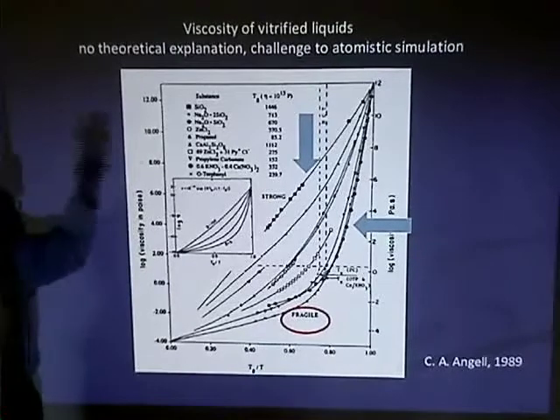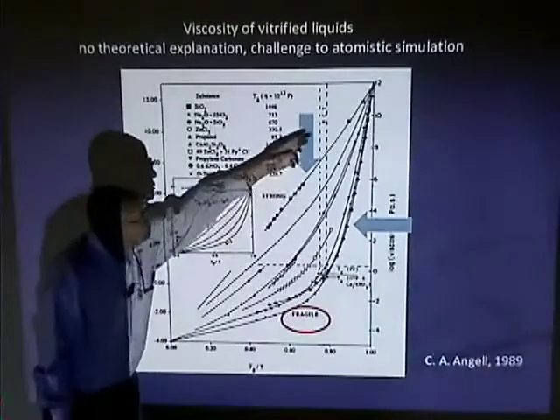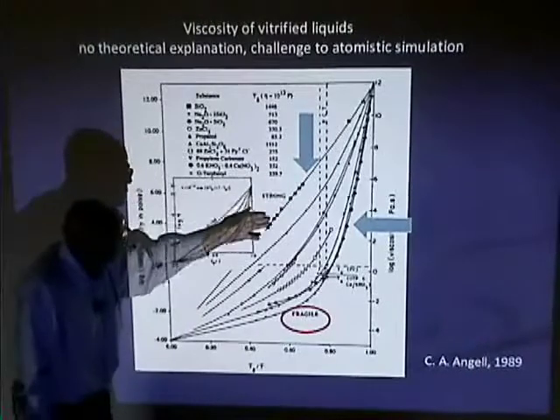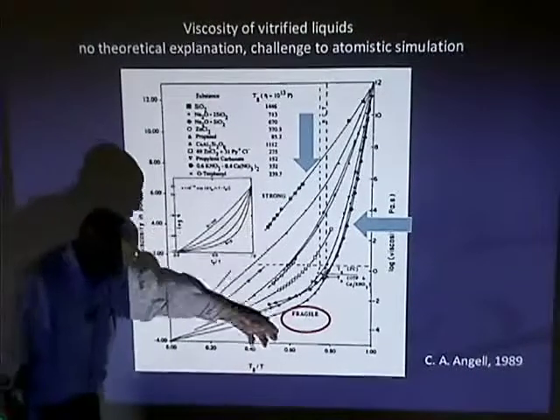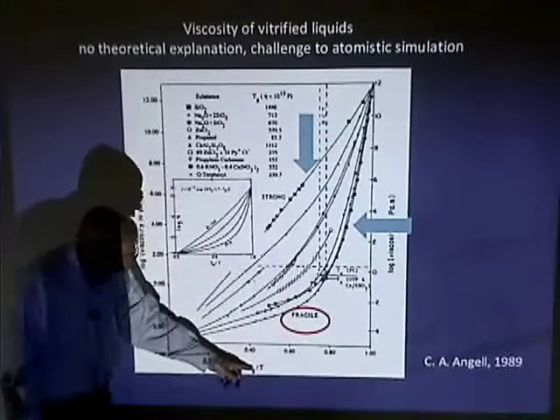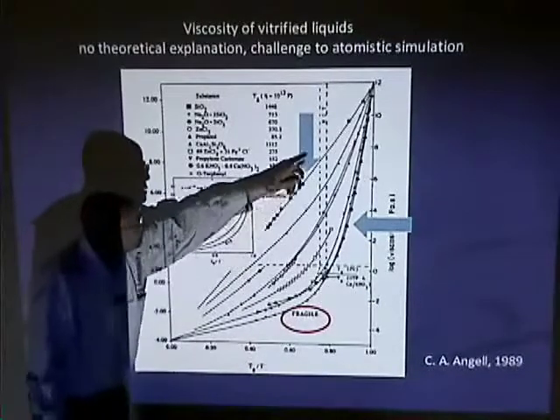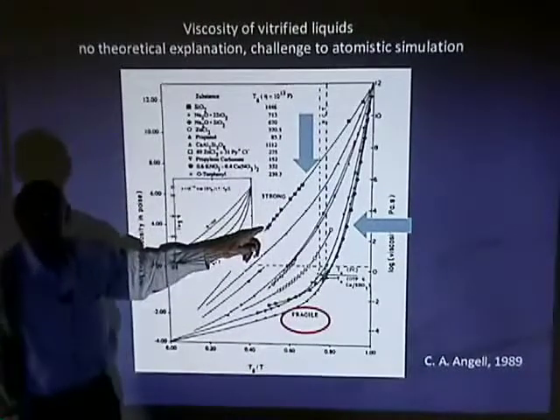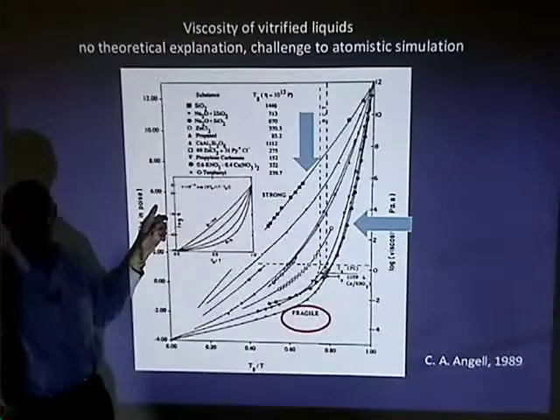So here's the silica data, I'd like to call your attention to. Silica data is, well, at low temperature - to the right of the scale is low temperature - and the data shows essentially Arrhenius behavior, because this is a log plot.